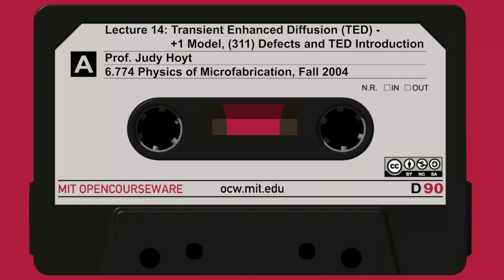So this was kind of an accidental discovery initially, but pretty soon people started to realize this is a tremendous benefit. Towards the end of today, we'll understand a little better where these interstitials are coming from. But anything you can do to create a sink for interstitials, be it high oxygen, though oxygen's not the best element to use. It also kills the minority carrier lifetime. So your bipolar transistor is not the best bipolar in the world. But neither is this one, where the boron base is diffused out completely. Carbon turns out to be a little better to use. You don't need as much, maybe only 1/10 the amount of carbon. And because it's in a lower concentration, it doesn't disturb the lifetime quite as much as the oxygen.